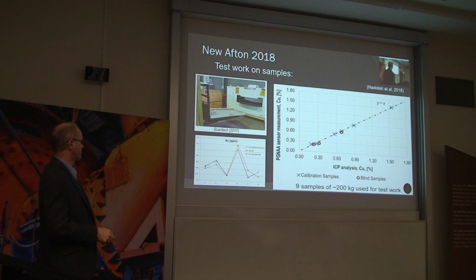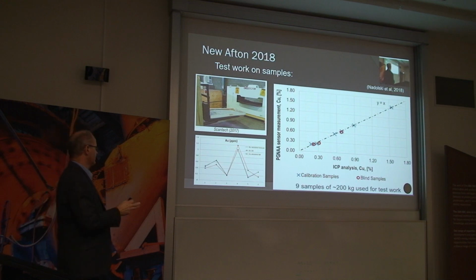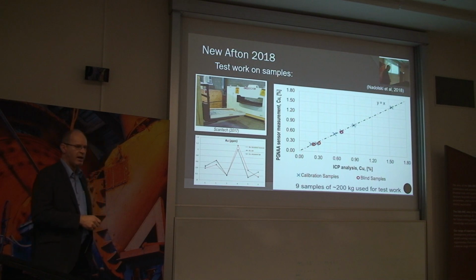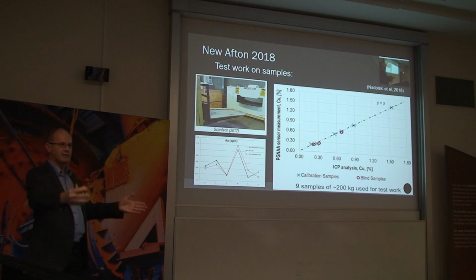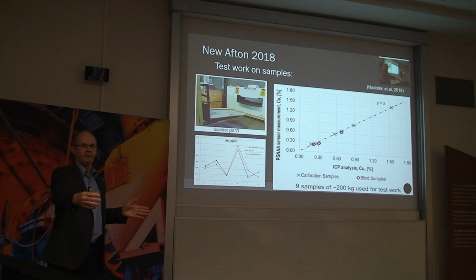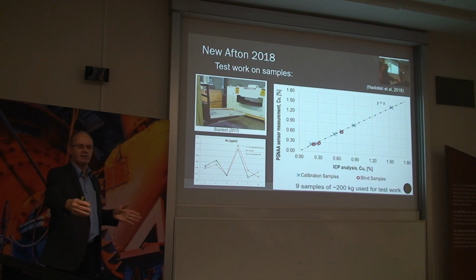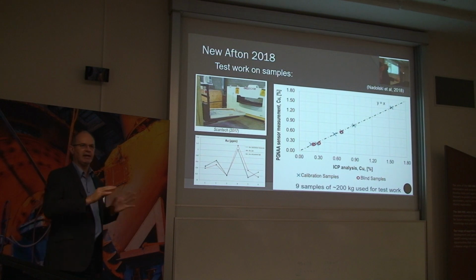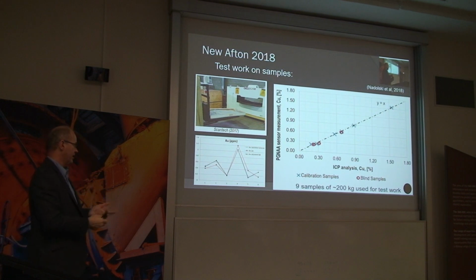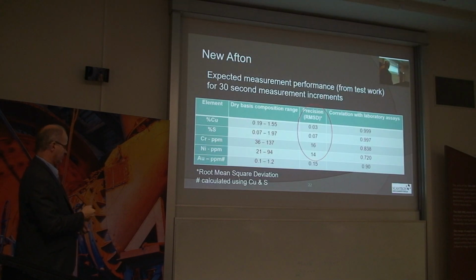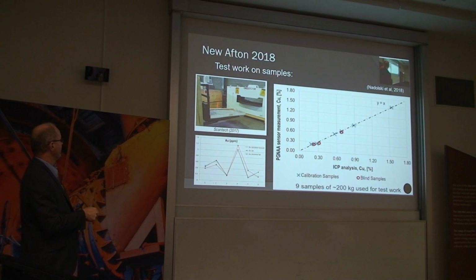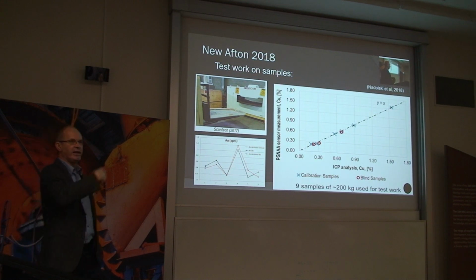Each sample was about 180 kilos to 190. The reason for that is that's the equivalent of 1 metre of conveyed flow at 1,000 tonnes per hour at that belt speed. Okay, because that's what the analyzer will see at any given point in time, so that's the sample size we asked for. The samples are tested in a production analyzer, so that analyzer is the one that would have ended up on site.